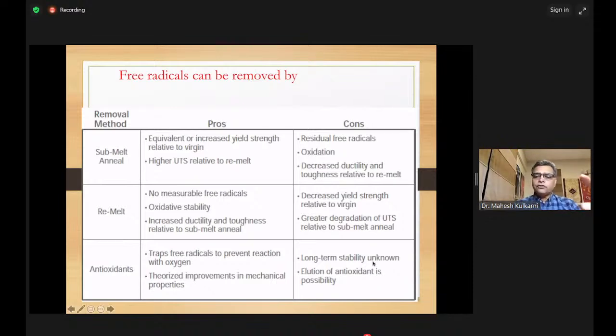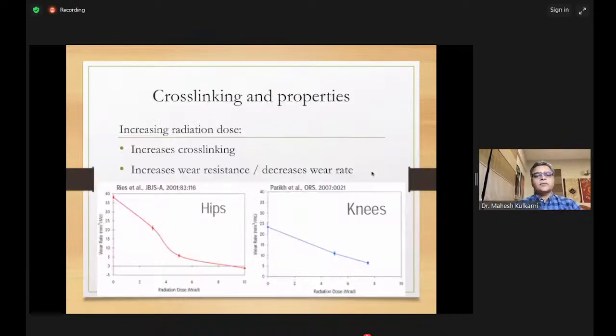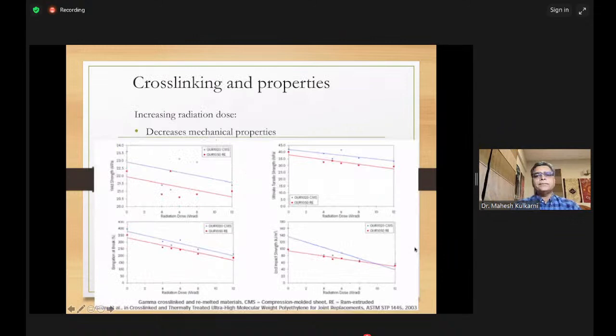However, elution of antioxidant is a possibility, and these elutions might affect the bearing surface wear. So we still have to look at what is going to happen with those. If you increase the radiation dose, the cross-linking increases, it increases the wear resistance, and it decreases the wear rate in both hips and knees.